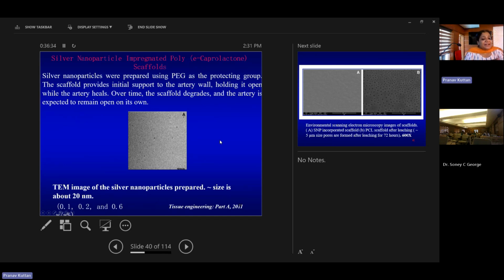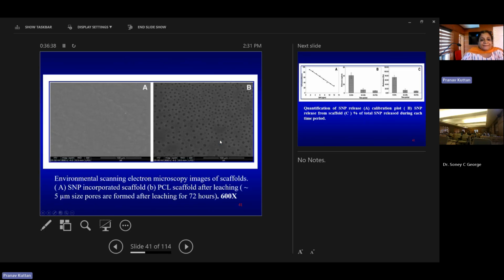So here also we tried different concentrations like 0.1, 0.2, and 0.6. The left side is the membrane, that is the vascular scaffold cut, and we have taken an SEM image of that membrane. And after putting that membrane for 72 hours, we can see different pores on the right side. That is because this PEG, which contains silver nanoparticle, has come out of the membrane. So it was found that within 72 hours, the maximum amount of silver comes out of this vascular scaffold.